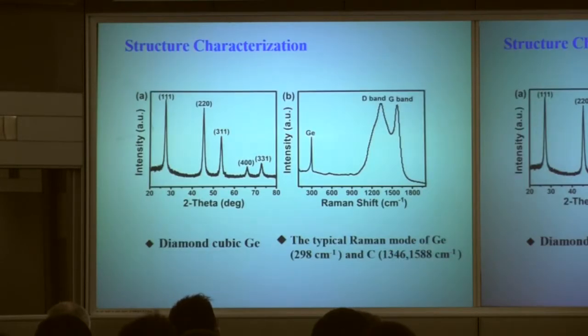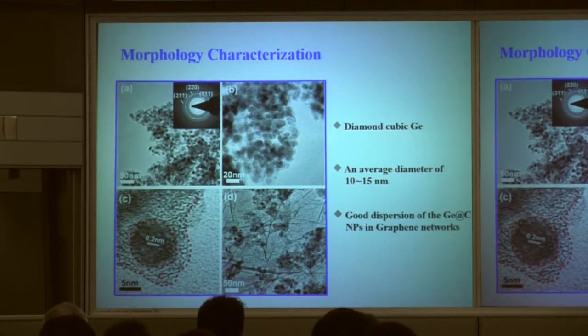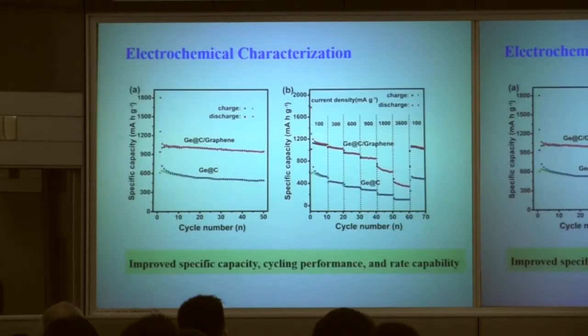Here is the result. First, you see here is the X-ray and the Raman, and here is the morphology characterization. You can find a very small nanoparticle. And for this nanoparticle, for example, here the center is the germanium, and here is the carbon. And at the end of this composite, here is the graphene. Here is a little bit larger area. You can find the graphene. Here is the nanoparticle. Here is the electrochemical characterization.